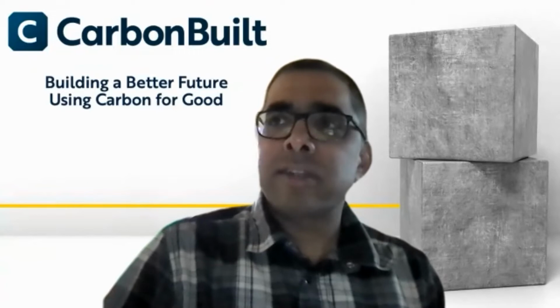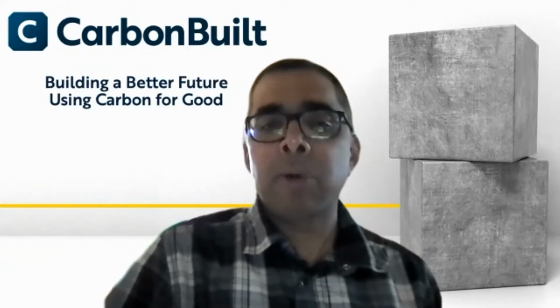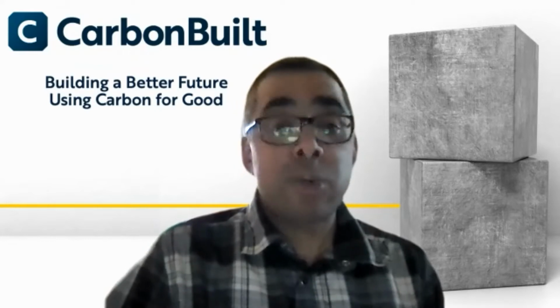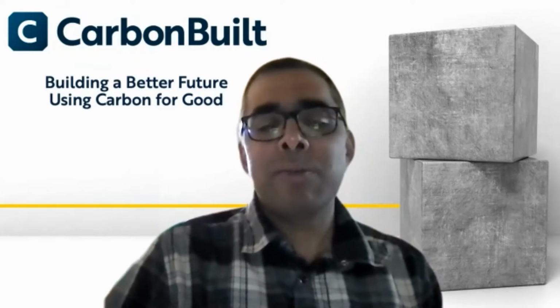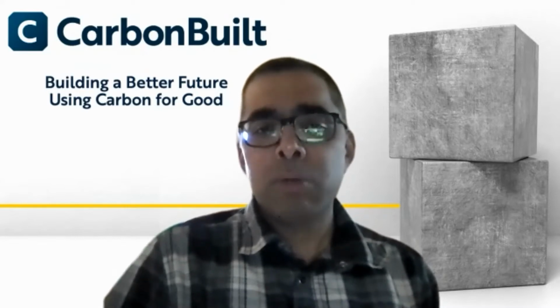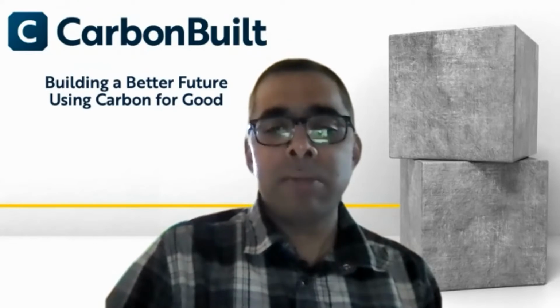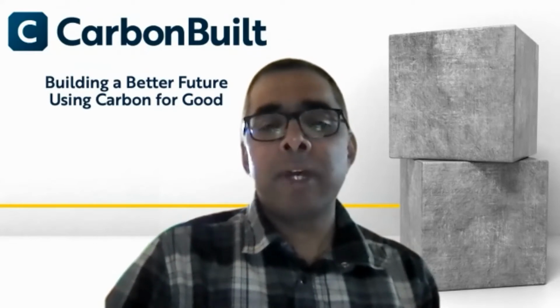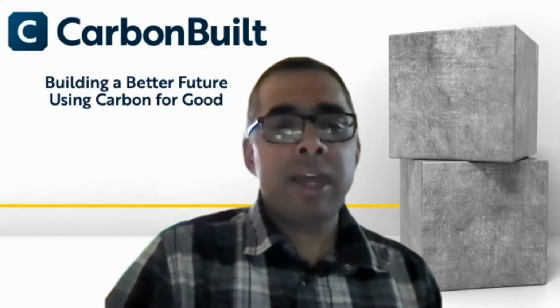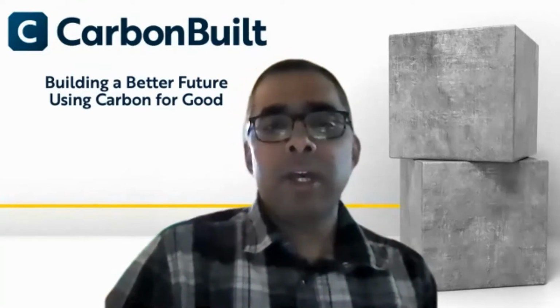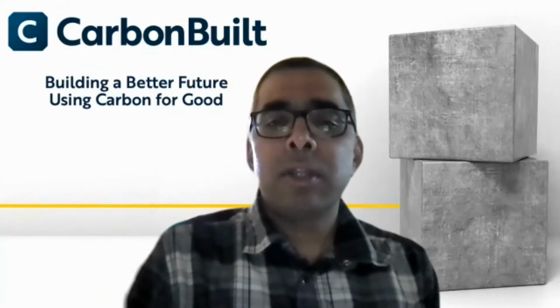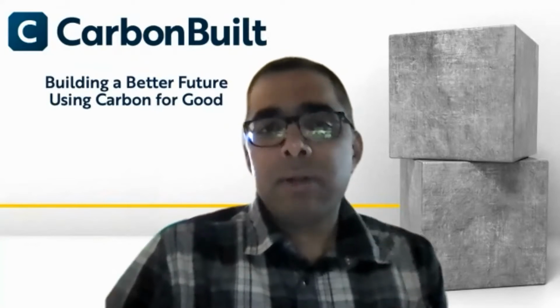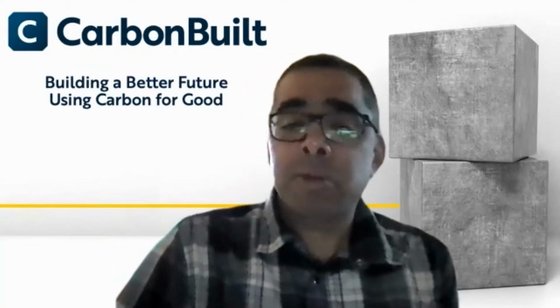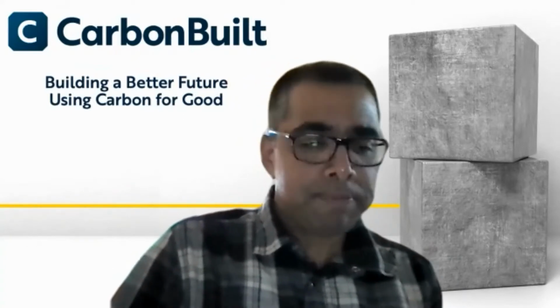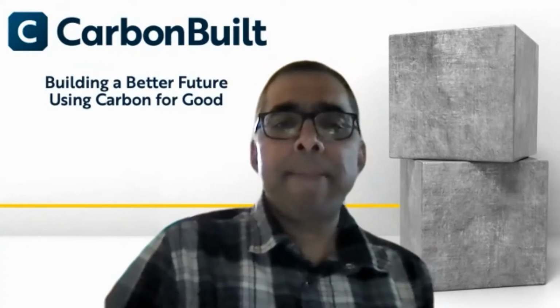So we look at this as something we can tailor depending on the product, and if it is reinforced, obviously we're adding a lot of calcium hydroxide to start. We can end with a buffer that is suitable for the use of that product, right? If the product is going to be used in a way that's more susceptible to conditions that would lead to that, we can have more calcium hydroxide buffer. And that's going to create more space for that long life carbonation to happen without having the problems, right? On the other hand, if it's not susceptible, we can dial it back, right? So is that helpful? Very helpful. Yeah, thank you.